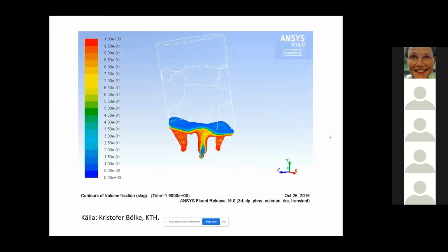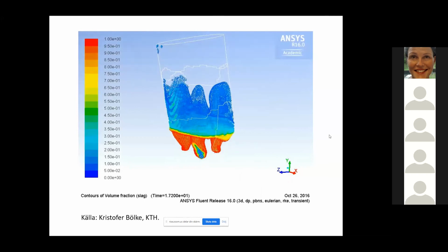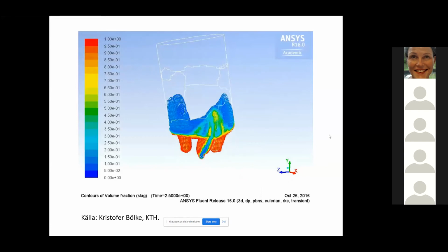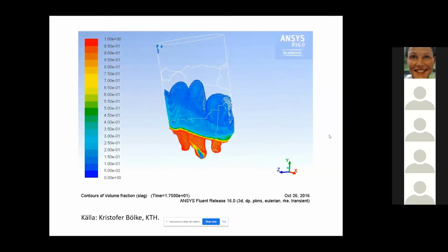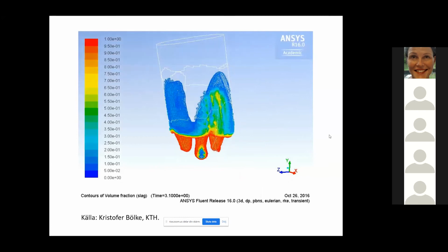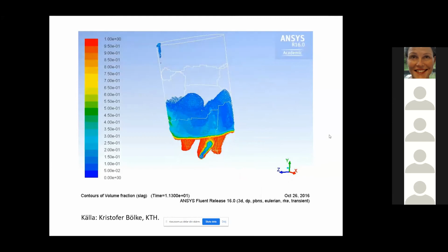What you see, I hope it works here. This is a modeling work from a PhD student that we had at the Swedish Royal Institute of Technology. What I want you to see here is the stirring activity inside the reactor. That is a quite heavy stirring when the gas enters the slag bath, and it creates this very intense stirring. And when this very hot bubble meets the liquid, all the thermodynamics and kinetics meet to extract metals.